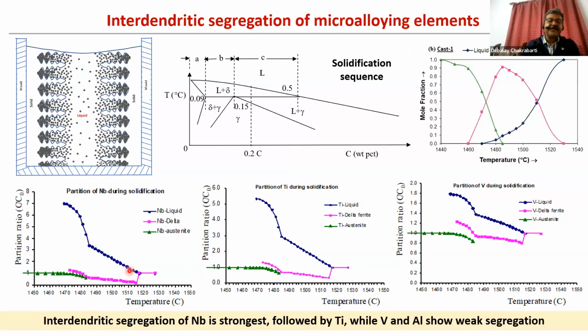But what happens is, as I said, that these elements like niobium and titanium go through segregation. Segregation means clustering of alloying elements at certain specific locations. Like when we do some cooking, if we add spice, we want the spice to be uniformly distributed in the soup. But if in some place it remains clustered, then that is really a horrible situation. So that is what is called segregation. And niobium and titanium can segregate up to 5 to 8 times the nominal composition. So if I am adding 0.05 niobium, in a certain region called the interdendritic region, its amount can be 8 or 7 times more than the average. And that is the biggest problem.